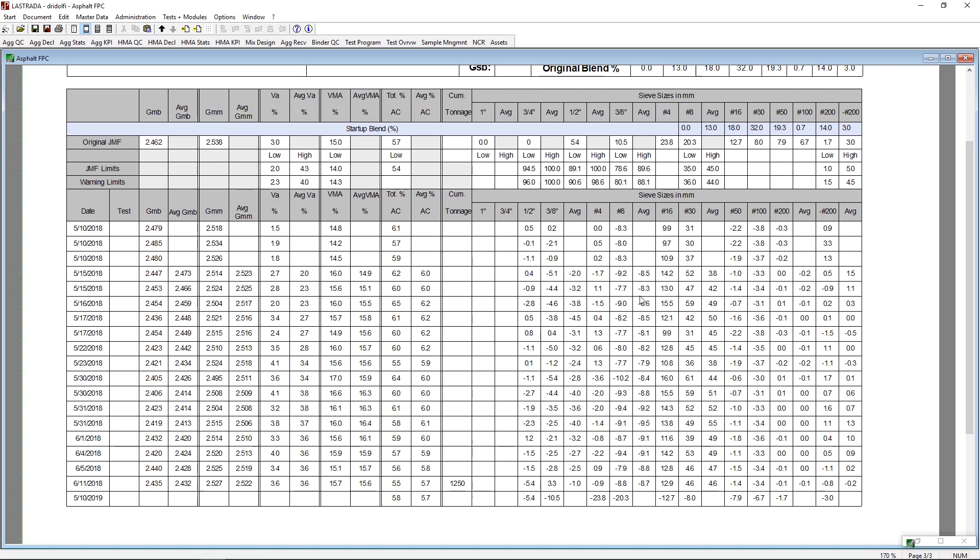And when you do that, you see the rolling average is doing exactly what is going on with the VMA. So, if I were producing this mix design, I would be really careful to understand how much material I'm retaining on the number 8 screen individually because it does seem to have an influence on my VMA.